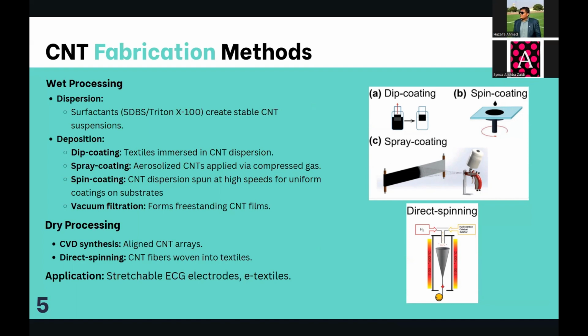We have dip coating, that is soaking textile into CNT ink; spray coating, blow CNTs onto fabric for even layers; spin coating, CNT dispersion spun at high speeds for uniform coatings on substrates; and vacuum filtration, that is create freestanding CNT films. For dry processing, we can do CVD synthesis, that is grow aligned CNT arrays onto the silicon, and direct spinning that pulls CNTs into fibers and weave them into smart textiles. An application of this is in stretchable ECG electrodes or in e-textiles.